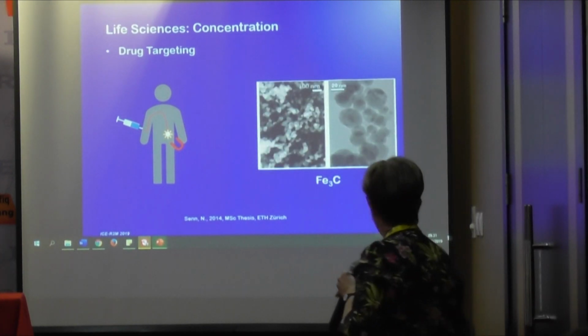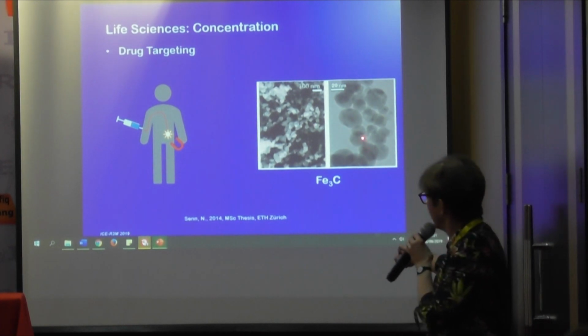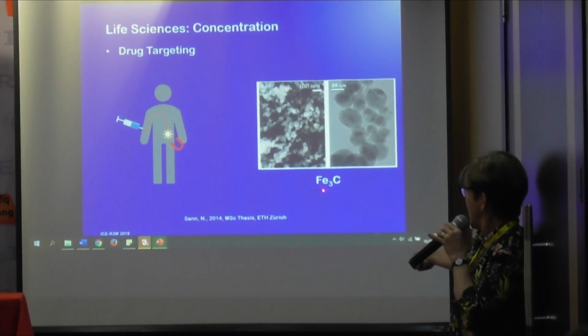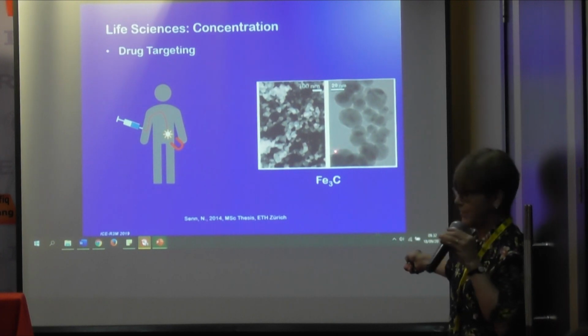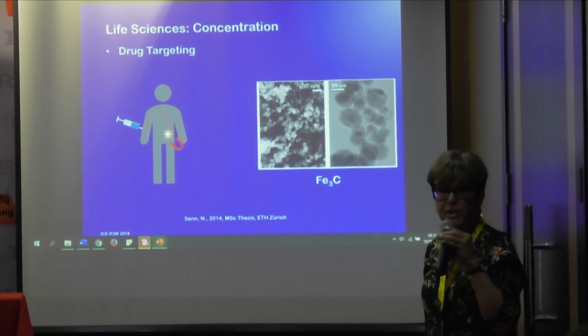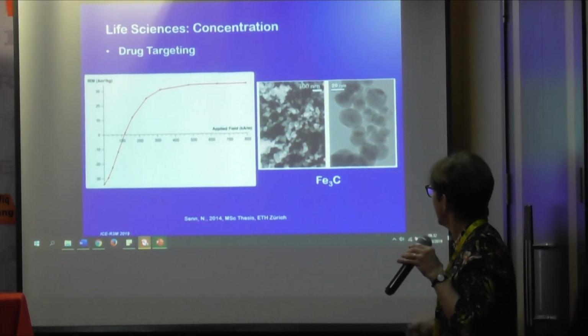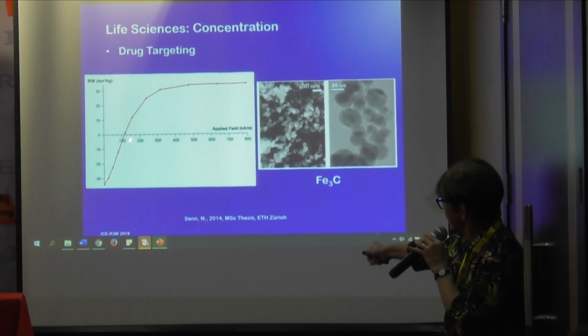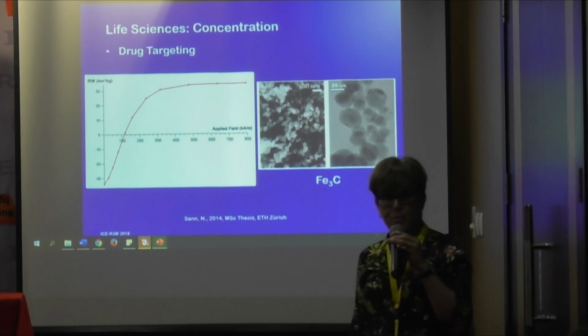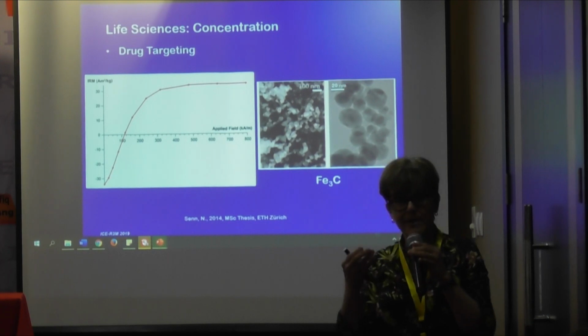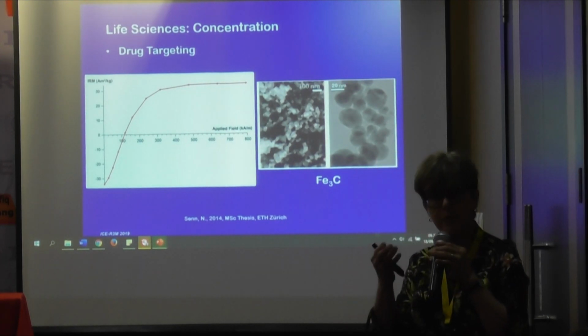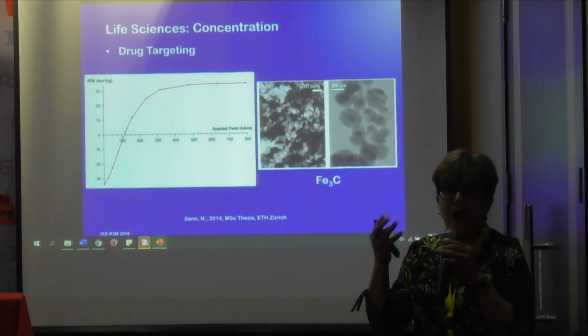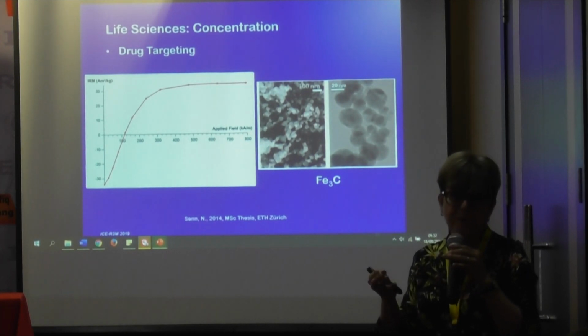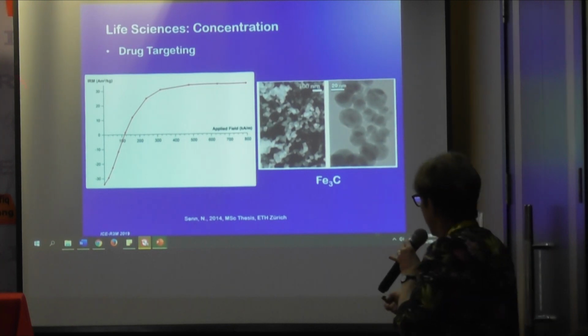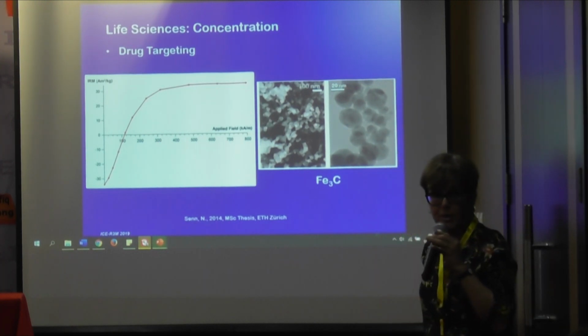Okay, next. So we worked with one group. What they were using for their magnetic nanoparticle was an iron carbide (Fe3C) cementite. It's on the order of about 30 nanometers. Next. We wanted to look at the magnetic properties of this cementite. The advantage of this mineral is it has a very high saturation magnetization. If you know magnetite, it has a saturation magnetization of 92 kiloamperes per meter. Cementite has 120, so it's about 30% higher. It also has a fairly high remnant coercivity.